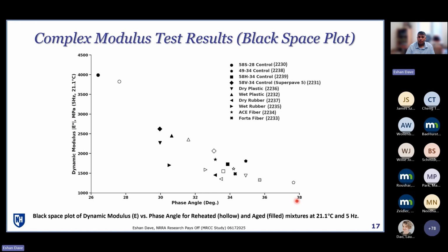But also equally important, they become less relaxant, right? Asphalt mixtures are viscoelastic, which means that when I strain them, after time, the amount of resistance or stress generated in them is really degrading or decaying. This horizontal axis represents how quickly these materials are able to shed those stresses. And we can see that their capability to shed the stresses is retarding or reducing as we age them. So bottom line, aging is really important when we are trying to evaluate things like cracking.